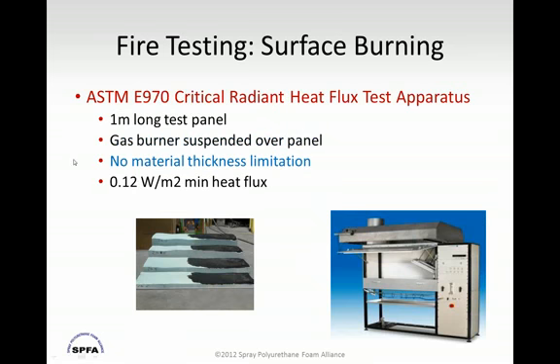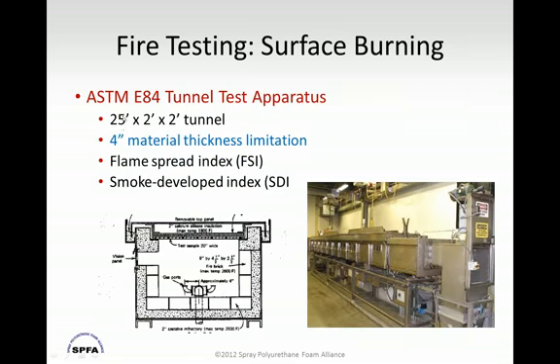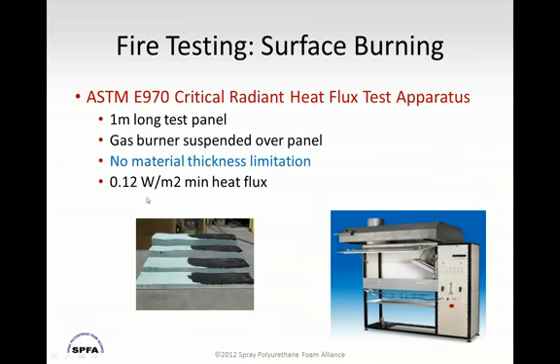The picture of the ASTM E970, the critical radiant heat flux test apparatus. You put a 1 meter specimen in here. There is a gas burner giving off a certain radiant heat, and if this product does not ignite and burn through the entire 1 meter length, then it's judged to pass that test. And what I should also note is that back here on this ASTM E84, there is a 4-inch material thickness limitation. So in this particular test, you can only put 4 inches of material from the ceiling of that chamber.